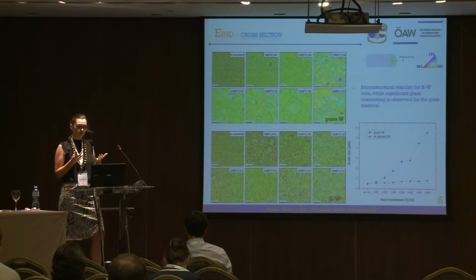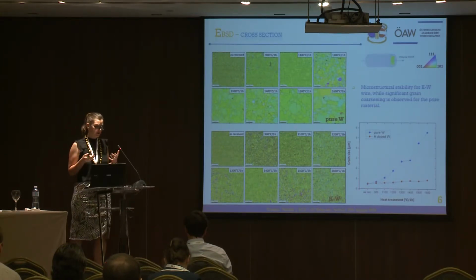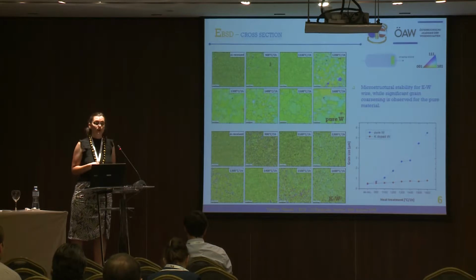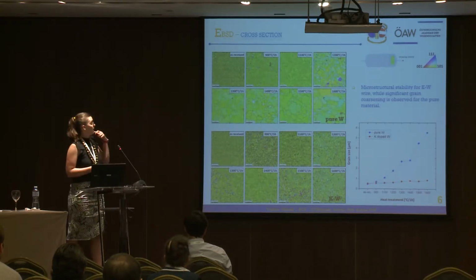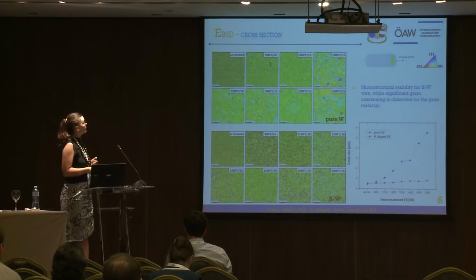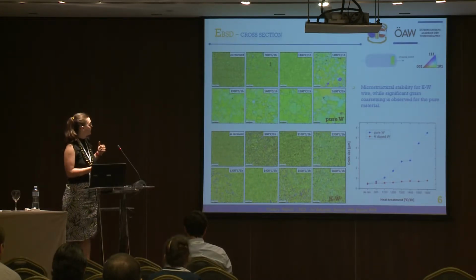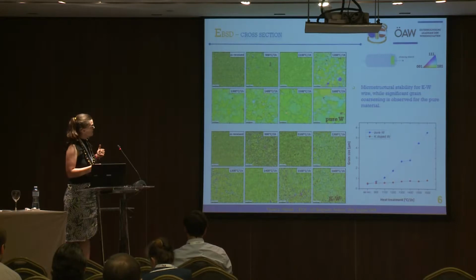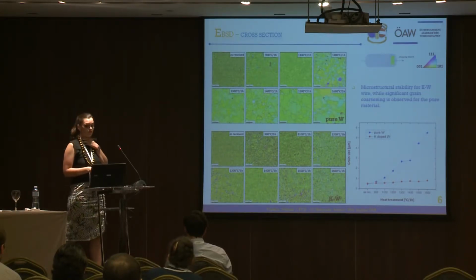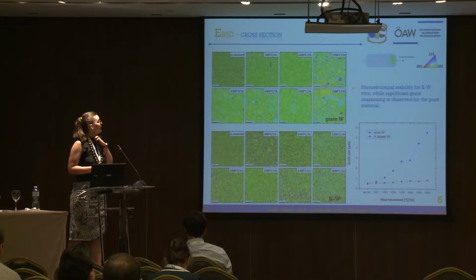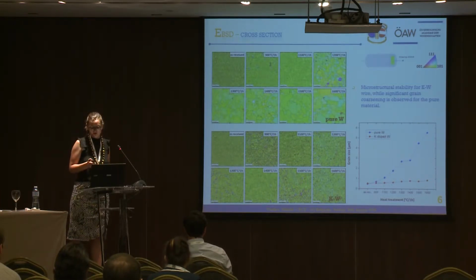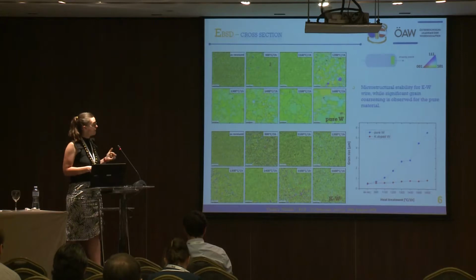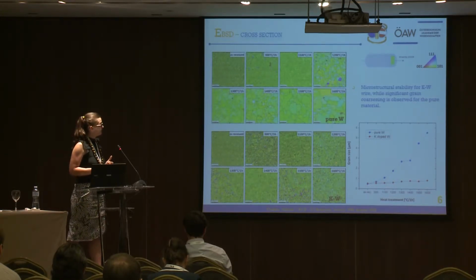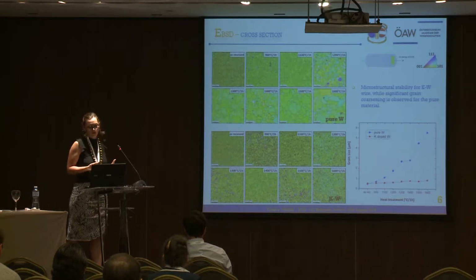So the microstructural evolution as a function of annealing was mostly characterized by EBSD, and here we can see that evolution. The top pictures correspond to pure tungsten, and here we have the potassium doped tungsten. This is the cross-section. If we follow the increase of annealing temperature, we can see that in the case of undoped material, there are large differences in microstructure upon annealing. So significant grain coarsening can be observed, and if you look at the graph, we can quantify this.